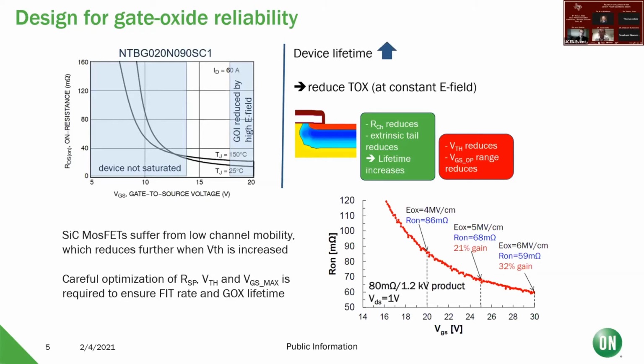Like in any semiconductor material, what happens at this interface, what happens right around the transition when the device turns on is rather critical. Mobility in silicon carbide is very subject to field conditions and intrinsically is not very high. So even though the material has its benefits of withstanding very large voltages before it breaks down, and so you can use very little amount of material to support high voltages, it does not have very great mobility. So the optimization on running the device for our on parameters or otherwise, need to be really fine-tuned right at the edge, I think, where lifetime and other fundamental reliability comes into play. Next slide.